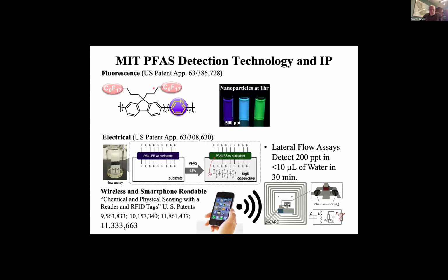What I'm showing here is a polymer. I'll show you more about this up above. It has perfluoroalkyls attached to it. This polymer is insoluble, so it's not leaching those, but they give it high selectivity for the perfluoro surfactants, or the PFAS materials of interest. We've also done this electrically, and the electrical system is quite useful because we have invented, and have a number of patents around, placing chemi-resistive materials, which change their resistance in response to a chemical, in line with the resonant RF circuits in passive RFID tags, which can be read and powered wirelessly, in principle even by your smartphone if you're looking for threshold detection.